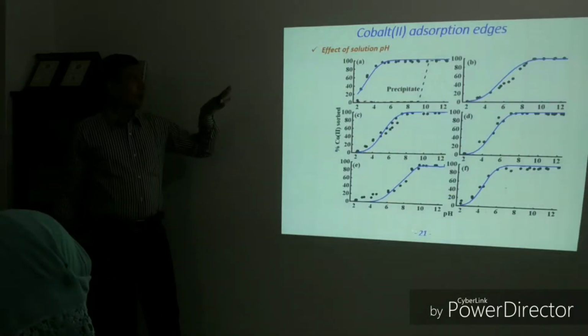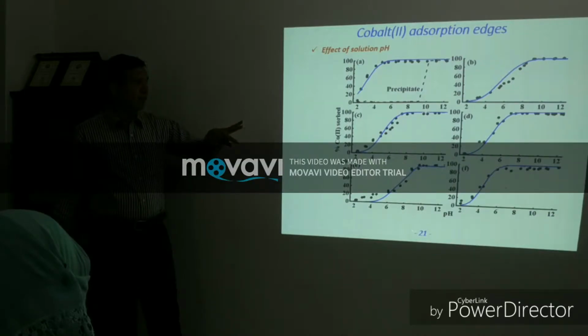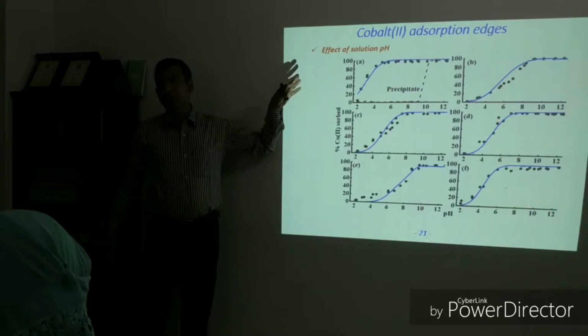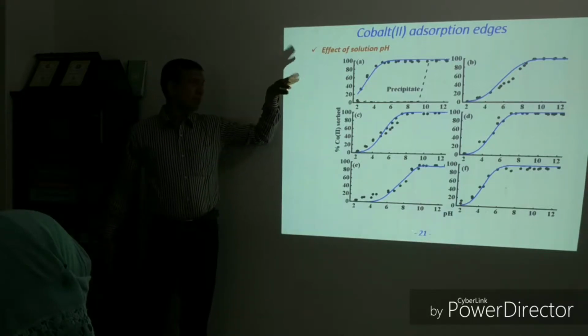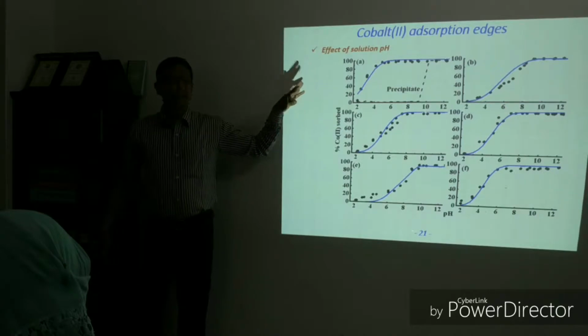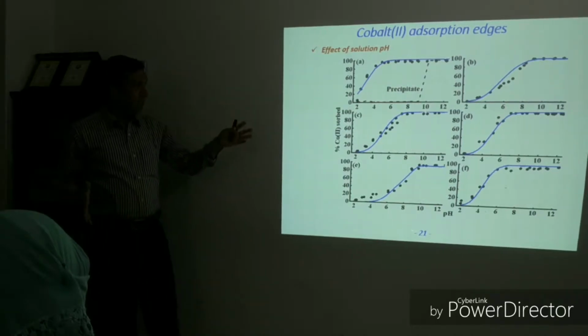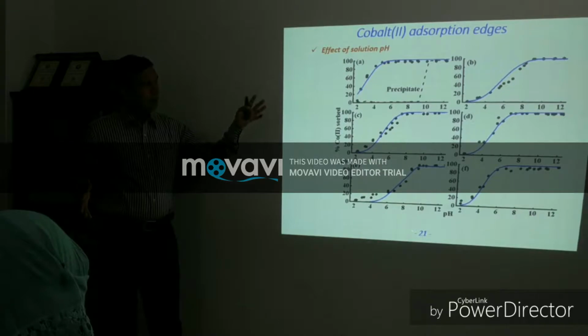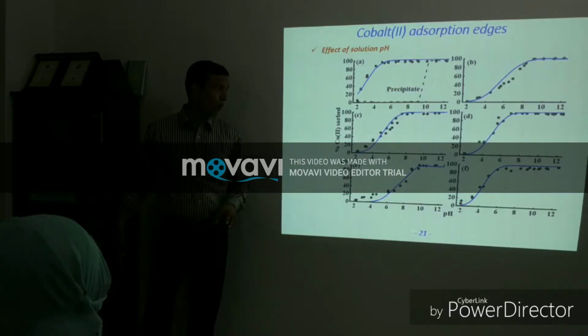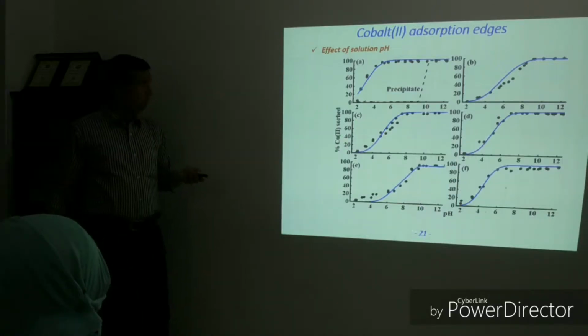Then adsorption edges, that means the effect of solution pH for 6 different substrates. So we see that at low pH adsorption is nearly zero, then adsorption increases and becomes almost 100%. This is due to the various surface properties, because each surface has a different point of zero charge. So this is likely to occur for every surface.